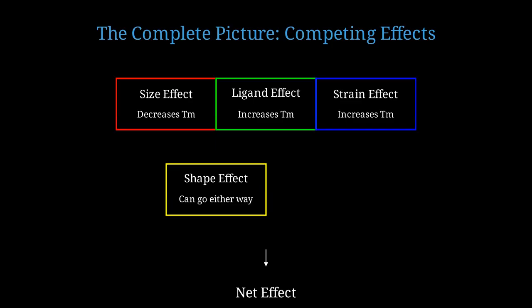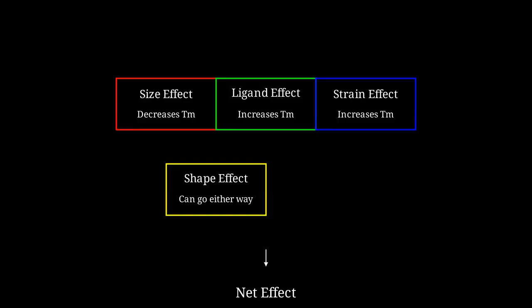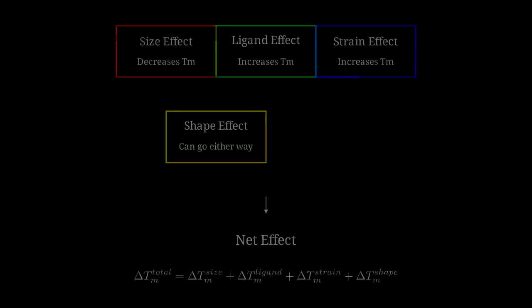Whether a nanoparticle melts at higher or lower temperature than bulk depends on the balance of all these effects. The size effect always decreases melting point. Ligands and strain typically increase it. Shape effects can go either way. The net result depends on which effects dominate. The total change in melting point is the sum of contributions from size, ligands, strain, and shape effects.